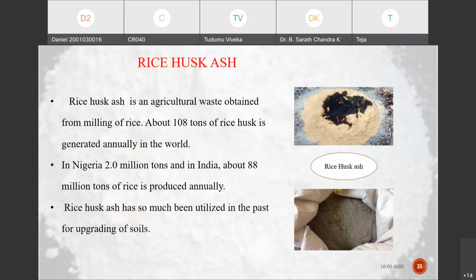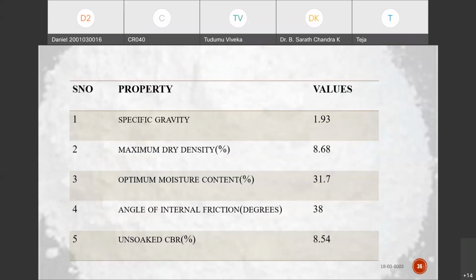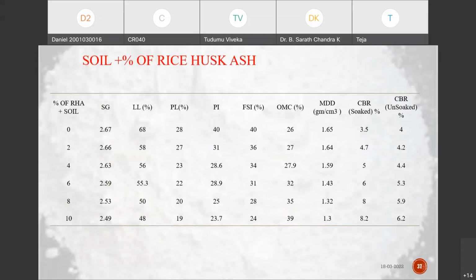Rice husk ash, the properties of the rice husk ash. Specific gravity is obtained as 1.93, followed by maximum dry density, optimum moisture content, angle of internal friction, and CBR of 8.54. And if we see the results of soil plus percentage of rice husk ash, these are the values obtained for specific gravity, liquid limit, plastic limit, plasticity index, free swell index, optimum moisture content, maximum dry density, etc., with different percentages of rice husk ash and soil.